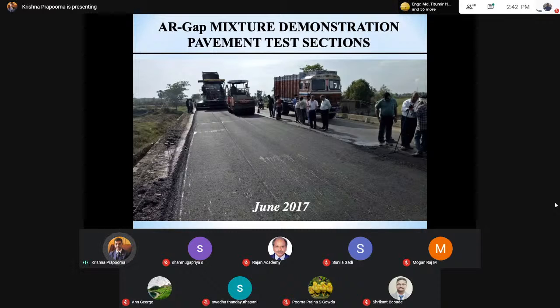Don't use vibratory roller. The reason is very simple. If you use a vibratory roller for thin sections, what happens? Your aggregates will start to get crushed. They will break into pieces. Your voids that you have designed in the gap graded, all of those will get filled up with these small particles. And you have defeated the purpose of gap graded or open graded, or for that matter, the thin section design. So very important.